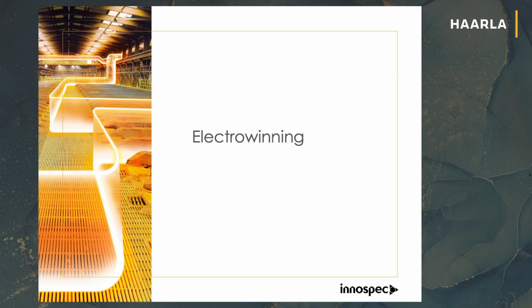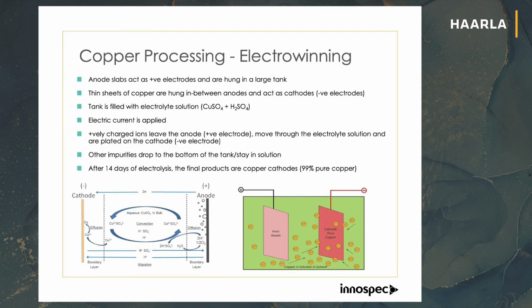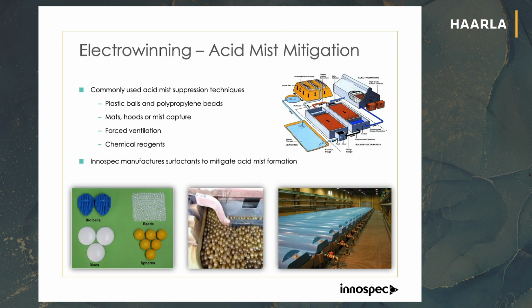I want to now move on to the electrowinning process and really about the acid mist. In here, as I've mentioned before, you get the bubbles formed on the electrode, and those bubbles then come up and burst on the surface. This can be treated in a number of different ways. There are physical ways and chemical ways. The traditional way was to put plastic balls onto the surface, which you can see here, which try and stop that mist breaking onto the surface.